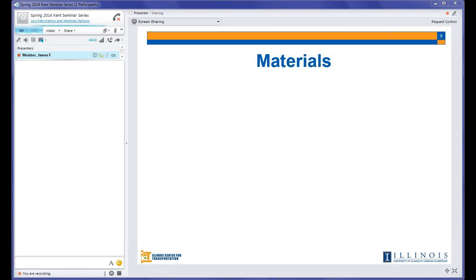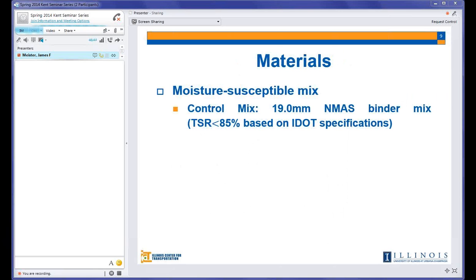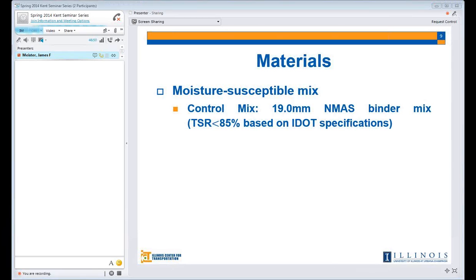Materials used in this study: we made sure that we use a moisture susceptible mix, and in this case it was an N90, 19 millimeter nominal maximum aggregate size binder mix. It was moisture susceptible based on the IDOT specification, meaning that the TSR, or tensile stress ratio, of this mix was less than 85%. In Illinois, if it is less than 85%, it is a moisture susceptible mix. And the samples were conditioned with only one freezing thawing cycle.